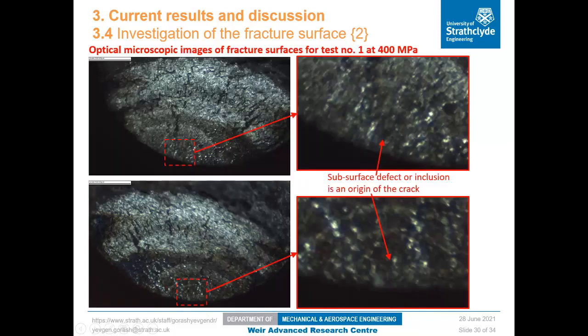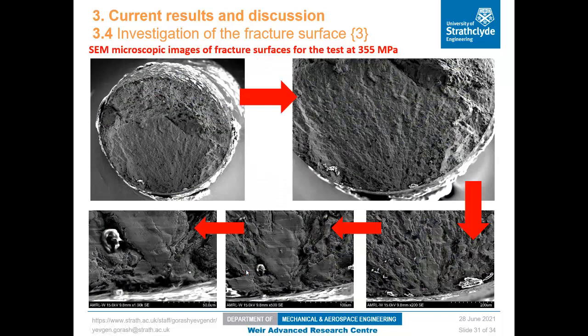The obvious advantage of optical microscopy is the coloring of the fracture surface that helps to track the crack growing path to its origin. The obvious disadvantage is the lack of focus and lack of resolution. The advantage of scanning electron microscopy is a perfect resolution, extremely high definition, extremely high level of details. However, the coloring is ignored. But with the combination of both methods, it's possible to identify the origin of the crack with quite high accuracy.